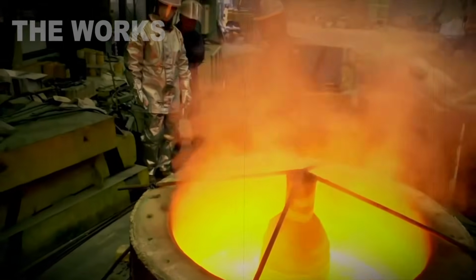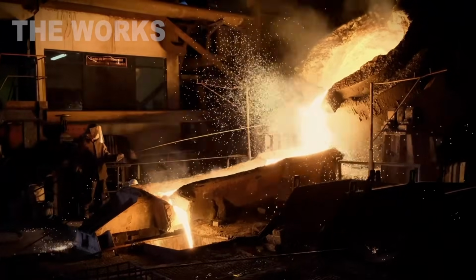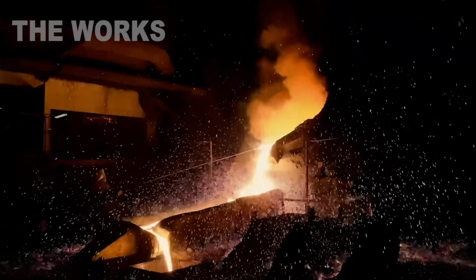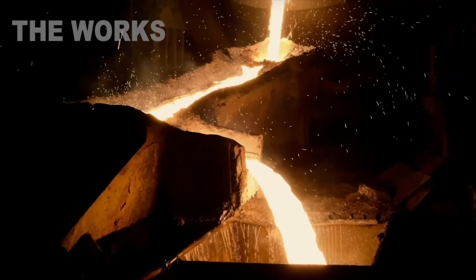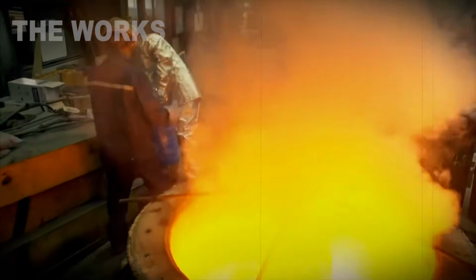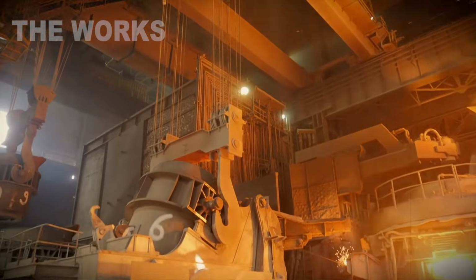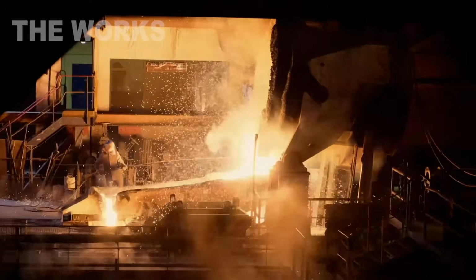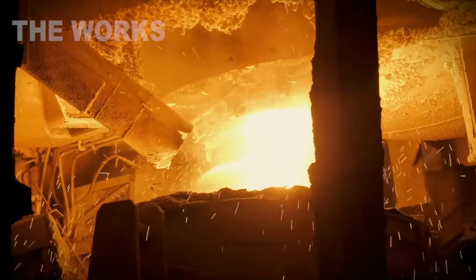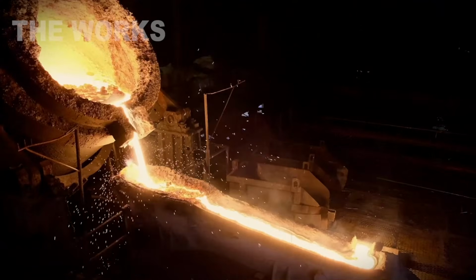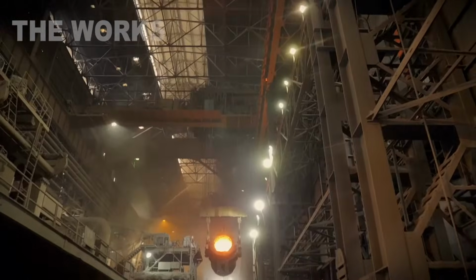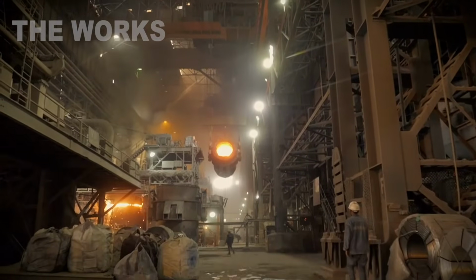The pour happens from a big ladle suspended from an overhead crane. They tilt the ladle, and metal starts flowing into the gating system of the mold. It looks like this, a thick golden stream with bright glow and a cloud of steam rising up. The air shimmers from the heat, and 30 feet away you can feel the hot wave hit your face. The foundry workers stand off to the side in protective suits and shields. Even several yards out, the heat hits your whole body. They control pour rate by adjusting the ladle tilt. Too fast and the metal churns turbulently in the mold, trapping air and creating voids. Too slow and the first portion starts solidifying before the mold fills, leaving internal seams in the casting. So the pace stays steady, continuous, dialed in by experience.